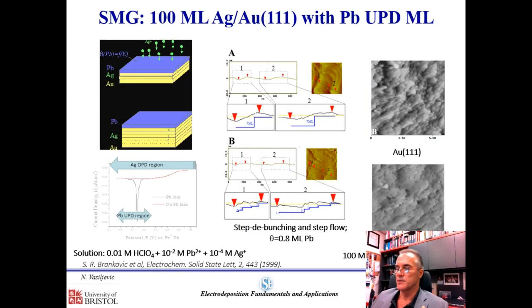And here's an example where we grow silver on gold, which is typically rough 3D growth, by using a constant current deposition, where the current or potential at which we are doing the process is designed in such a way that at the same time, while we are growing silver in the overpotential deposition regime, which means we are in overpotential for silver growth, we are also at UPD potential for lead, which really means that we can have a stable lead monolayer on the growing silver surface.